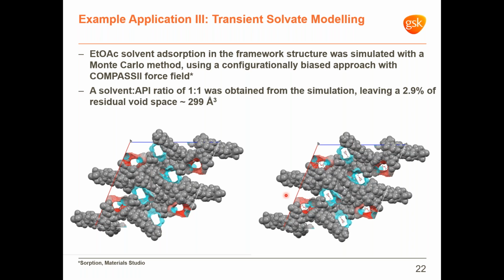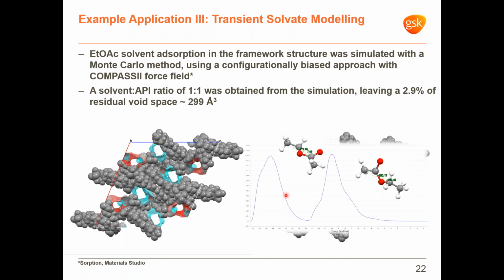Although the 1.5 to 1 experimentally suggested solvent to API loading ratio was attempted in several simulations, it could never be achieved, and the 1-to-1 loading ratio was the highest achieved, leaving a residual estimated void space of about 300 cubic angstroms. It's interesting to observe as an output of the simulation the bimodal distribution of the sorption energy, presumably corresponding to the solvent uptake in the two symmetry-independent channels, in which the solvent seems to adopt a different conformation.